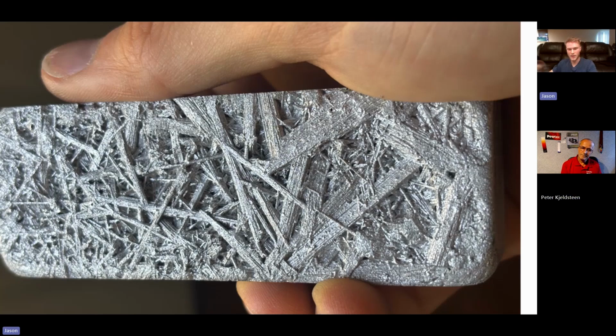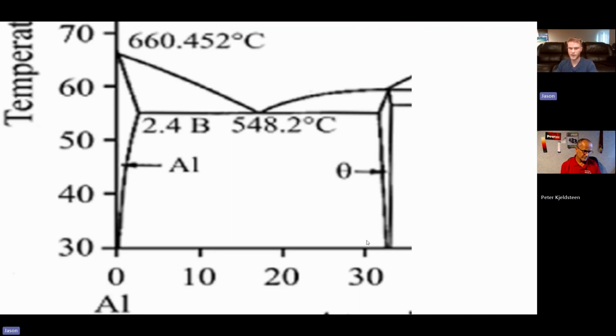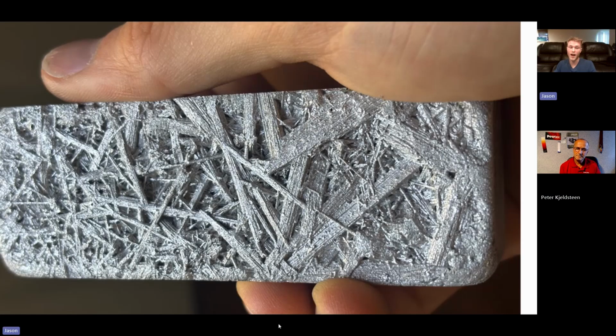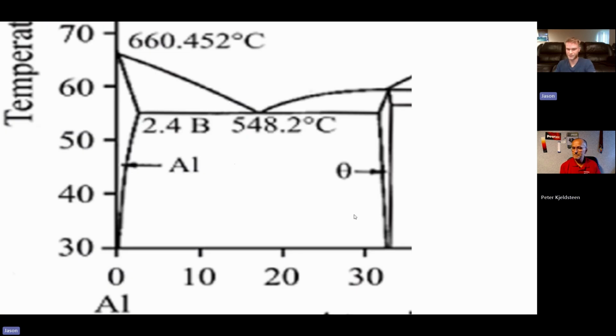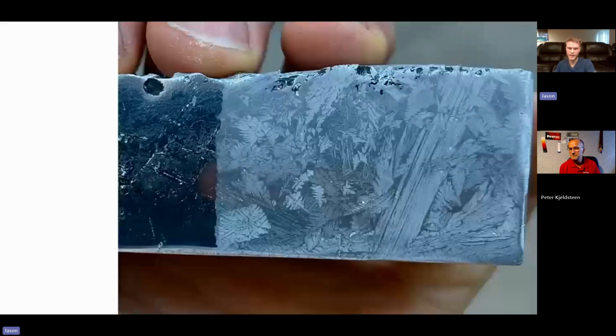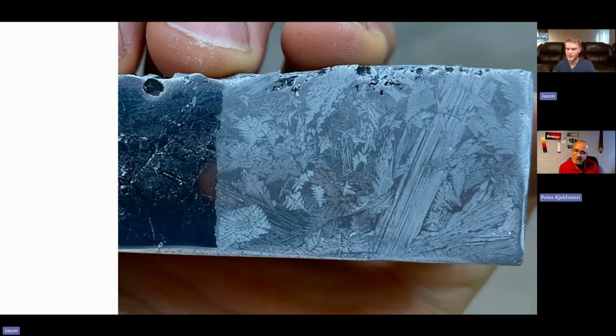And so what I wanted to try with this is doing a very slow cool of this compound at approximately 30% and see if I can get a Widmanstätten-like pattern. Because again, these really long rods are the hallmark of Widmanstätten. And so I tried that out, approximately 30%, cooled very slowly, especially slowly through this region, and remained slow. And this is what I got the first time. And this is actually etched. A lot of dendrites. Yes, a lot of dendrites.